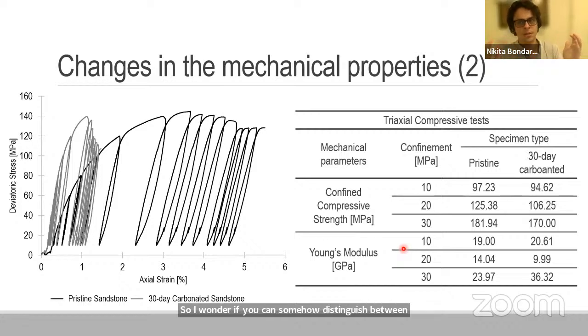Yes, of course. I wonder, you were referring to pristine versus 30 days carbonated and 60 days carbonated. Can you somehow distinguish between the effects of heterogeneity and the effect of treatment? If you tested different specimens, they might have inherent variability of properties. Have you tried, let's say, measuring permeability on a pristine specimen, since permeability measurement is not destructive, then conducting the treatment, and then measuring it once again?